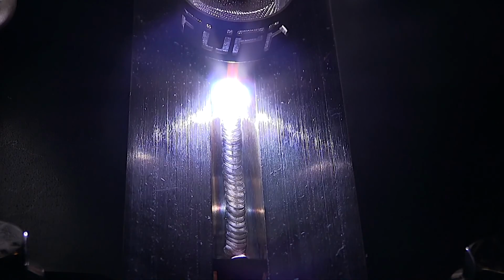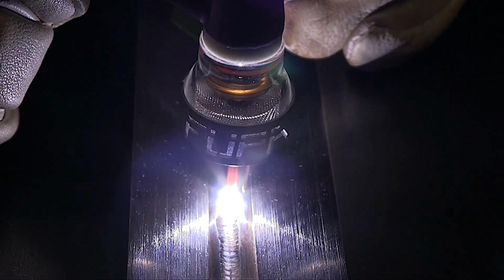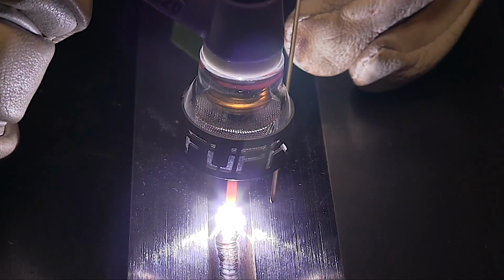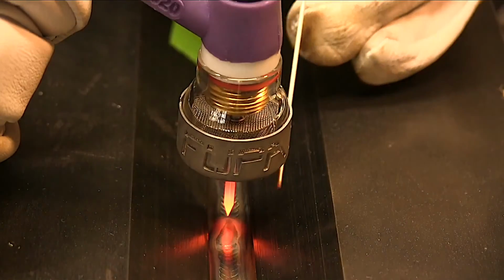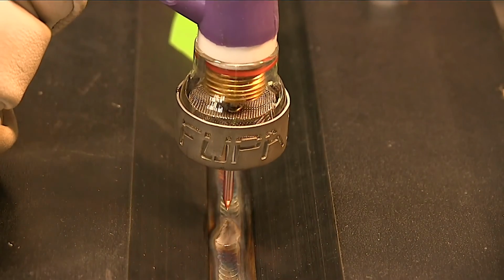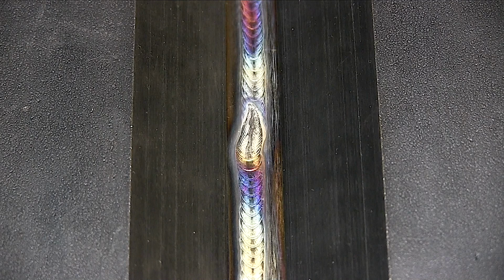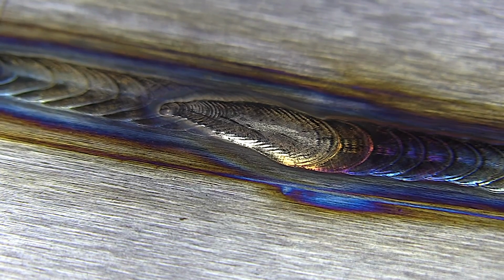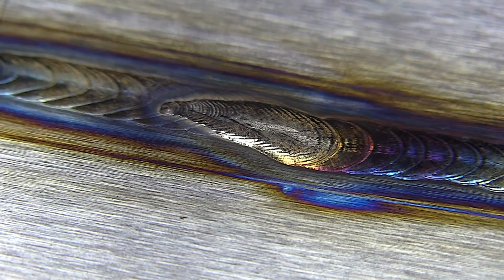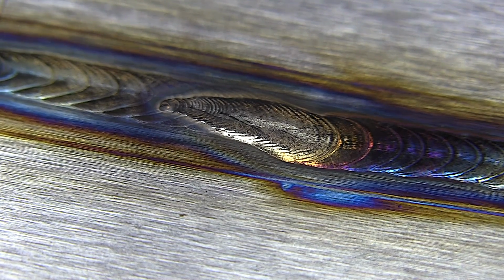And then when I tie into the previous weld here, I just keep the torch moving, add less and less filler, and kind of comet trail on out. And that wound up being about the best technique I could find for crack sensitive alloys like Inconel 718, 4130 chromoly, or 15-7 PH stainless.